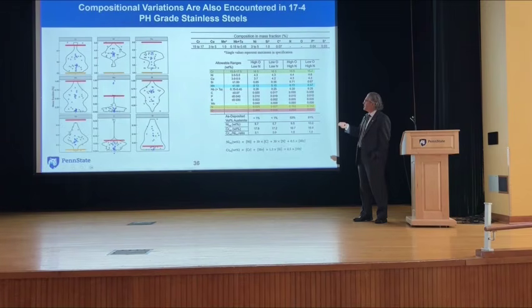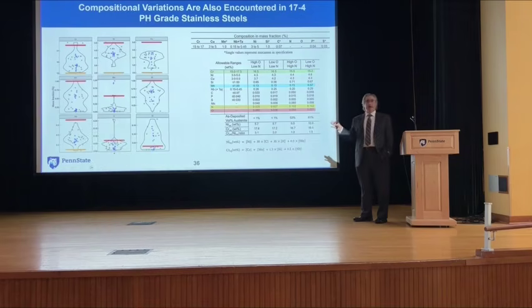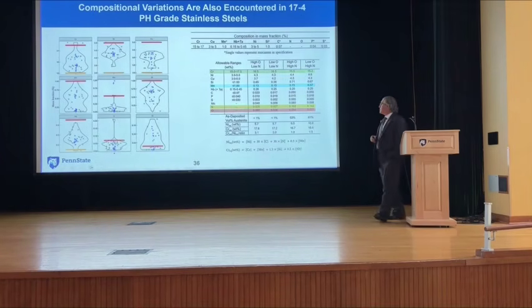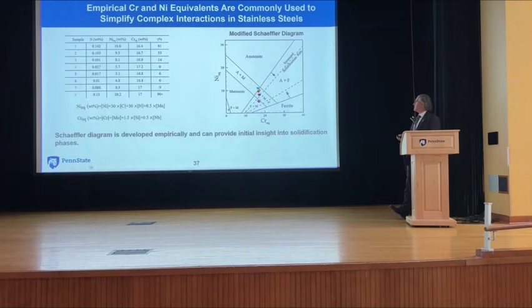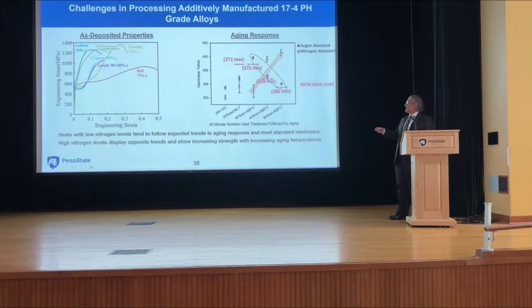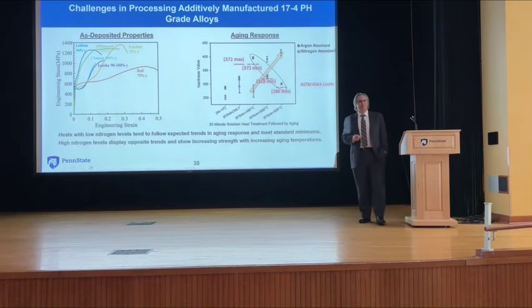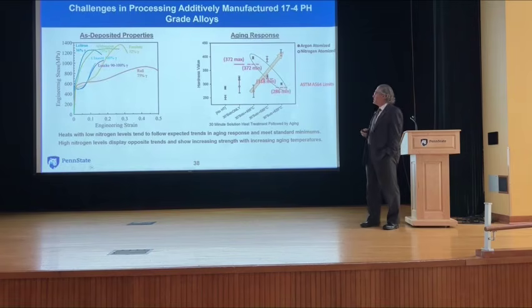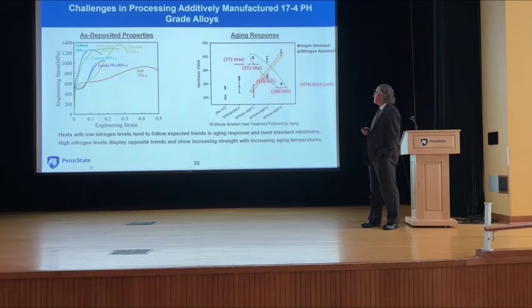But you start looking at the heat-to-heat variability in even these, and this is just in powders. This is just a small subset. They can vary significantly. What I want to tell you is that these are the differences in the mechanical properties out of them. And that's just ones we grabbed out of the literature. And these are additively manufactured, powder bed fusion, pretty standard alloy. So I don't know as a designer how you're supposed to be able to do that.